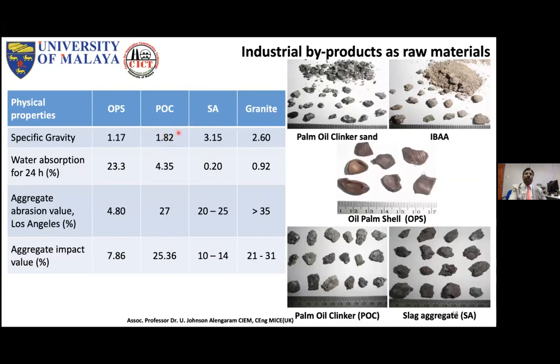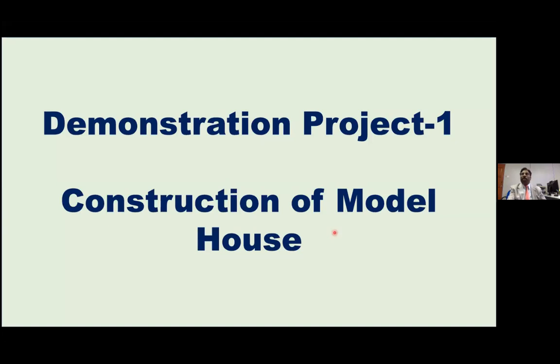It's very low compared to 3.15 and 2.6. Compared, also the water absorption is slightly higher. You can add more water because of this. And this one, you see, the aggregate impact, of course, it cannot withstand because it's porous. It's very porous. So that's my answer for this. Then I can see another question.